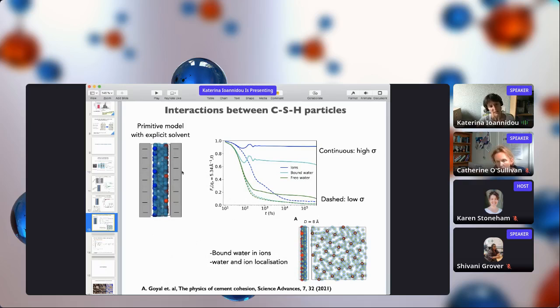Here we see this layer if we remove the charged planes, viewing it from the top. From the scattering, we see that with low surface charge, the water and ions can freely move in this plane, whereas with high surface charge, both the water and the ions are localized on the plane, and this is what causes the very strong attraction between the calcium silicate hydrates.